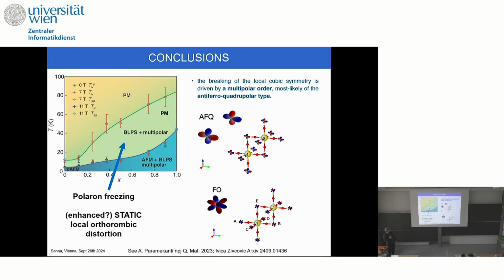Before that, I would like to mention the very nice talk of Arun, who developed the model, including considering the impurities in the system. As I told Arun, if muons can be considered as impurities, probably we should expect that the magnetic transition temperature is different, while here the transition temperature from the muon spectroscopy and the one from NMR coincide within the error. Probably, I don't know if really the muons can be considered as particles which create a big effect in the system. Probably not. This is my view from the experimental point of view.